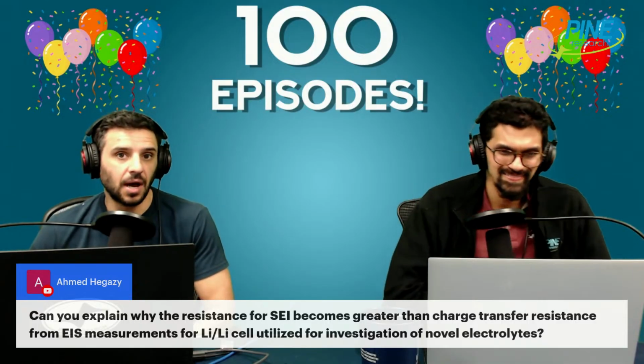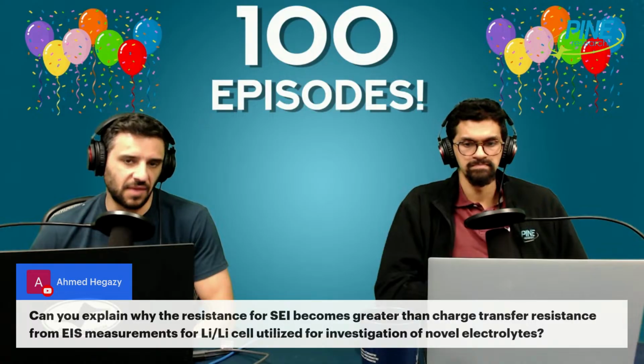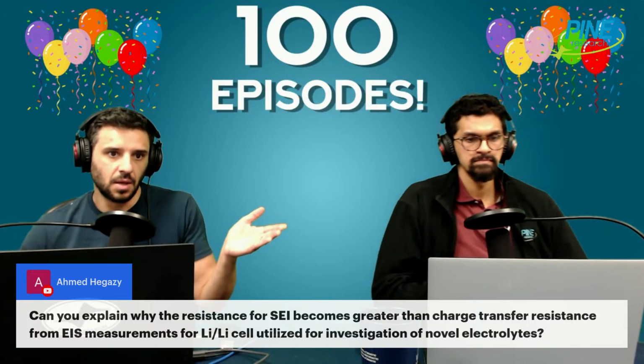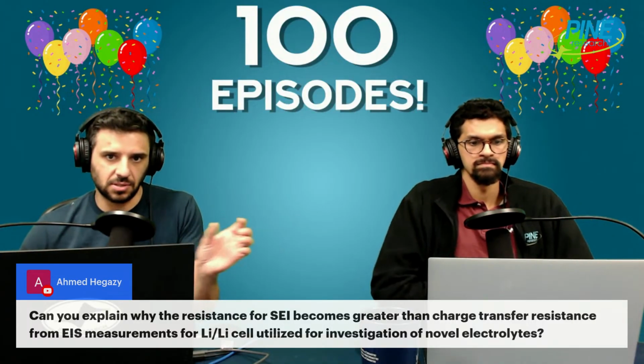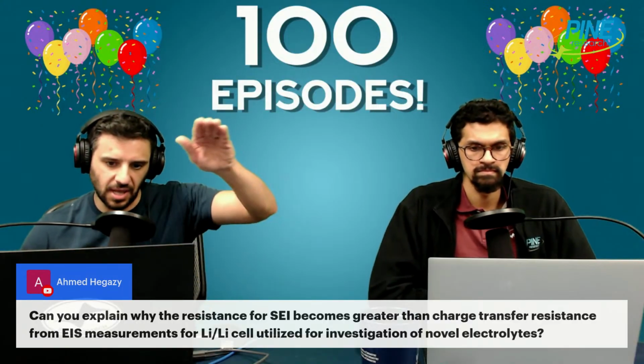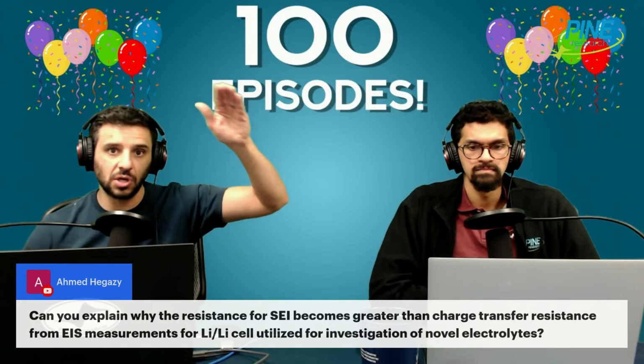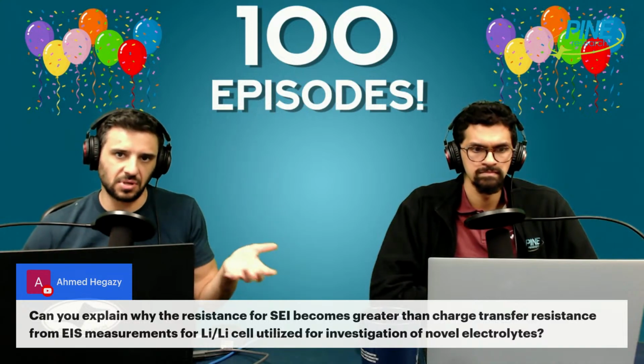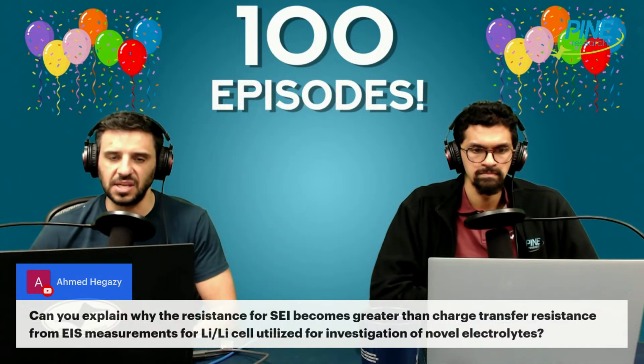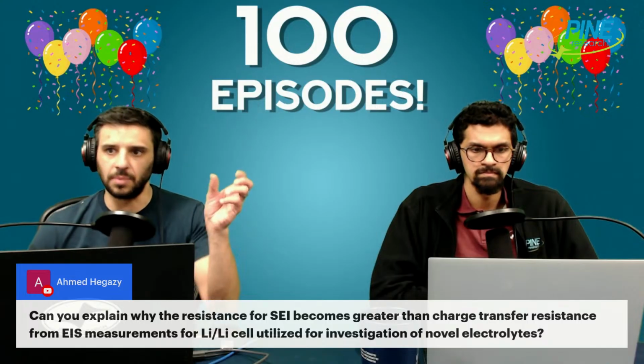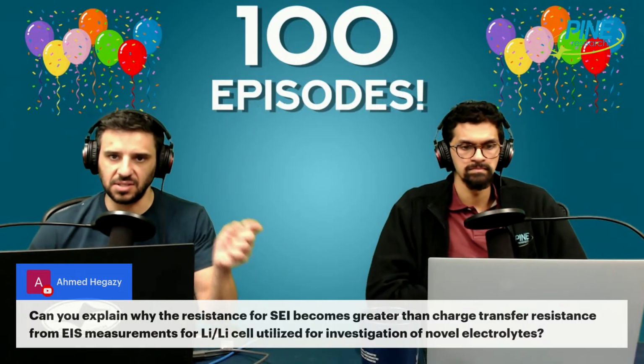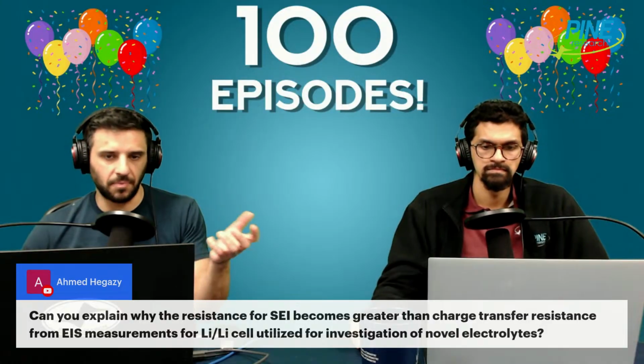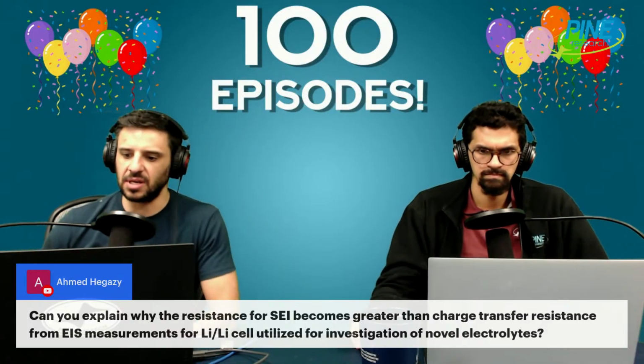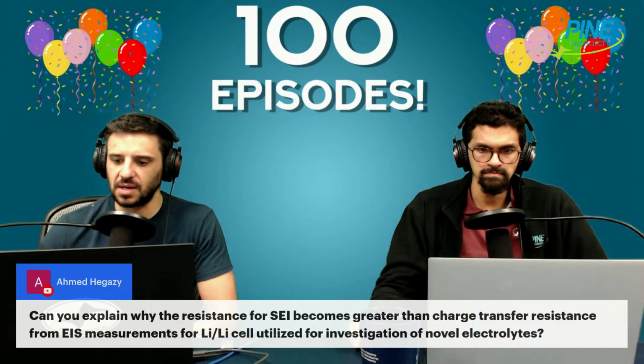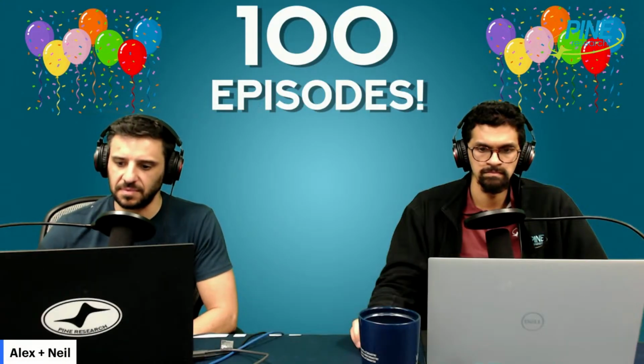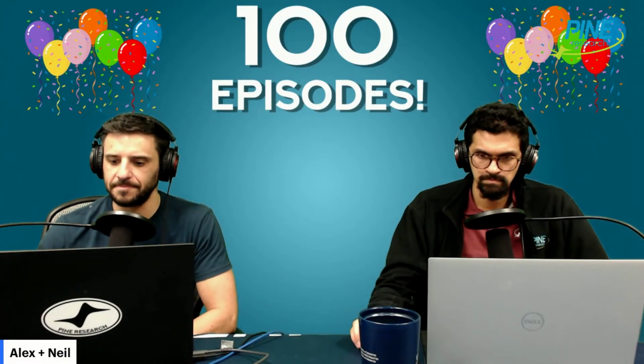That can happen. And so in those cases, you need to do something if you want to differentiate between the processes occurring at two similar time constants, so they look like one semicircle instead of two. You've got to do something like DRT, distribution of relaxation times, which is sometimes needed in those cases to determine how many charge transfer processes you actually have when they're a little bit indistinguishable in the Nyquist plot. So that's hopefully some food for thought for you on those phenomena.